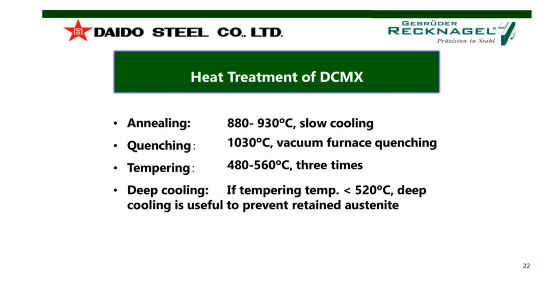The quenching temperature is about 1030 up to 1050 degrees, and the tempering temperatures between 480 and 560 degrees. You have to use 3 times tempering, but this is, I guess, an absolute standard in Germany and in Central Europe. And it's important to use a tempering temperature to stay on the right side of the secondary hardening maximum. Because if you use a tempering temperature lower than 520 degrees, you will create some retained austenite, and therefore you have to make sure that the retained austenite switches into martensite.